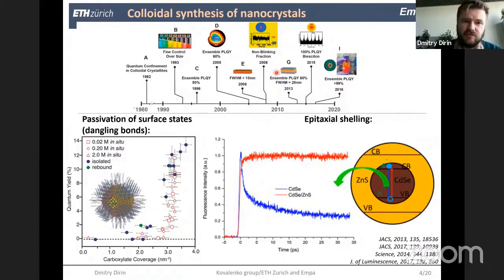And knowing all this history, we can summarize that two very crucial things to make bright colloidal semiconductor nanoparticles are, first, surface coverage, so a good passivation of surface states, because if we reduce the number of ligands on the surface, then the quantum yield also quickly goes down. And the second important thing is that if we want to make really bright particles, then we need to make core shell structures. When we are talking about conventional semiconductors like cadmium selenide based, again for the same reason, because we need to passivate surface states on our optically active core, and we also need to isolate all possible defects from this optically active core.